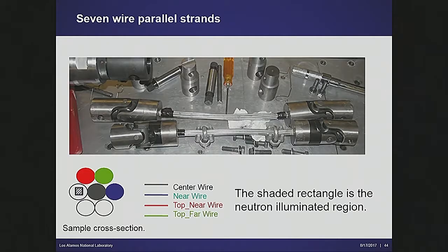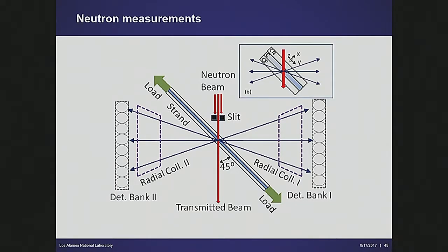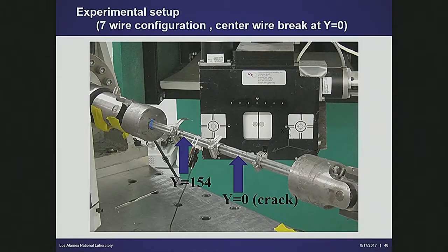And so one of the classic neutron problems is that suppose I've got a clamped bundle of cables, and a cable in the middle of this is broken. I'm wondering, how far along the central cable or the surrounding cables can I see that there's a break in here? What you can do is define a sampling volume. You can put a load on this set, set up a situation which is probably fairly familiar by now: slit, sampling volume, radial collimators. Now you can ask what's the strain that exists in multiple places. You put a crack in the middle, you load it up.